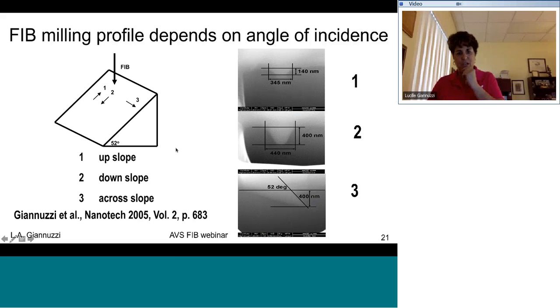And this also shows some work that I did several years ago, showing what happens when I mill up a slope versus down the slope versus across the slope. So milling up a slope, because the interaction volume or your collision cascades are always below the beam, the collision cascades are being pushed down the angle. You're always creating sort of a new feature. Going up the slope, it's quite shallow, but if you mill down the slope, you're always overlapping the previous collision cascade, and so you can actually go a bit deeper, and then across the slope, of course, you generate a pattern which is consistent with the initial slope.